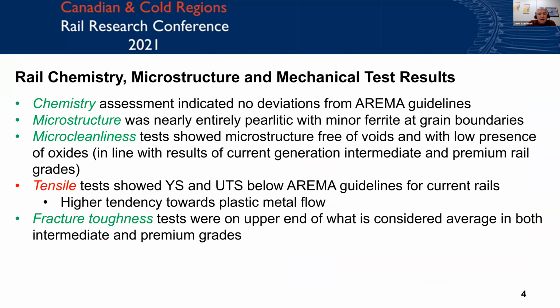We looked at the microstructure. The microstructure was entirely pearlitic, which is the expected outcome from this type of grade. There was some minor ferrite at the grain boundaries, which was totally fine because this was hypoeutectoid rail, slightly hypoeutectoid. The microcleanliness was very good. This rail was free of voids. We didn't see any type of cavities in it.